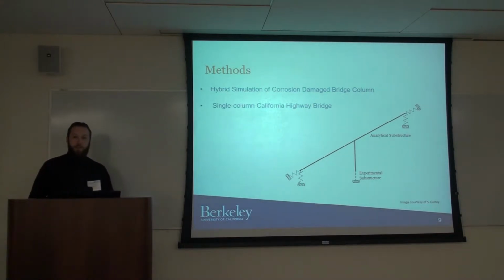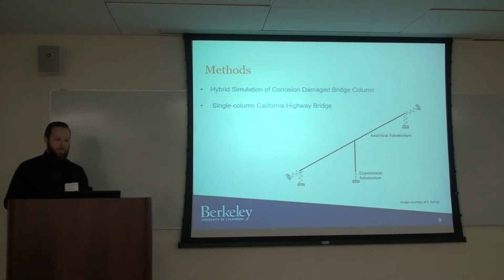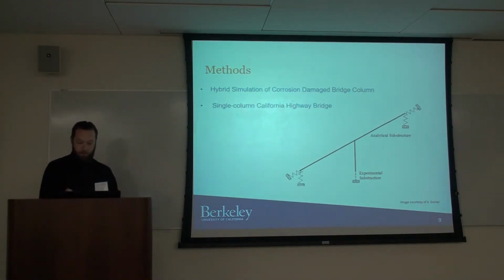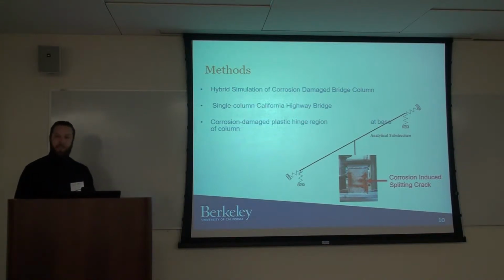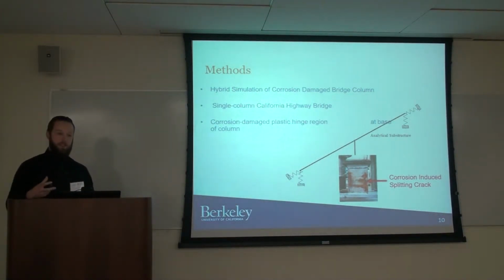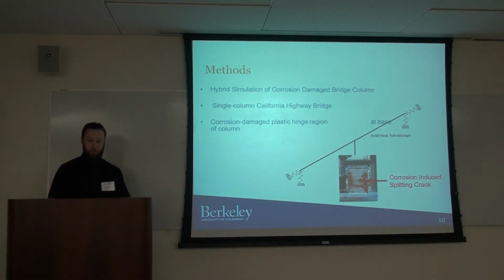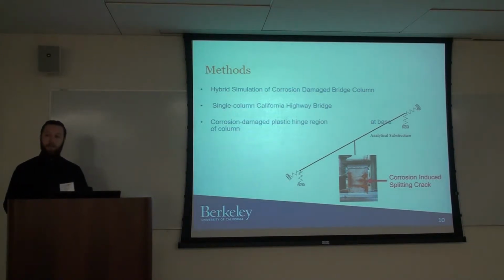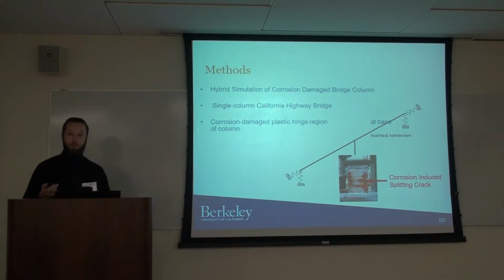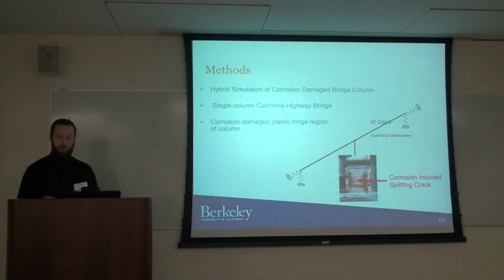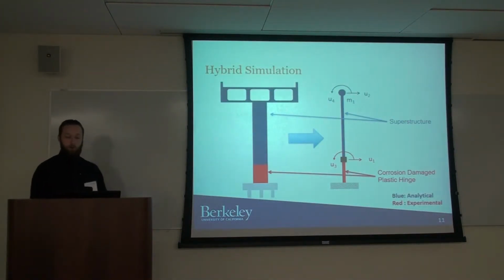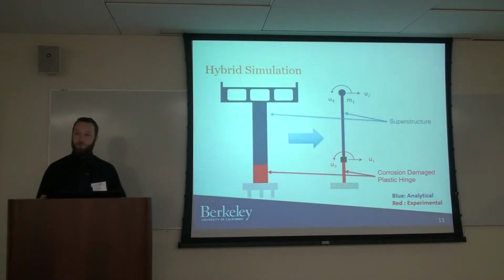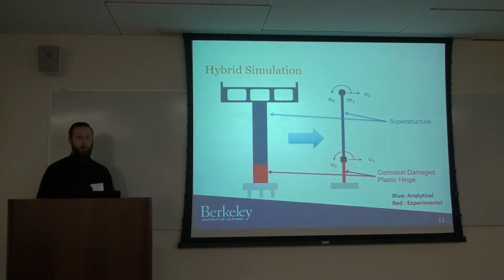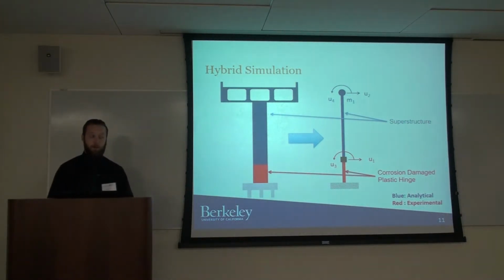So the bridge of interest that we're considering is a single column California bridge structure. And we see that we have an analytical substructure, and we've replaced the plastic hinge with an experimental substructure. This is just a concrete column section, and it has been separately corroded and with splitting cracks induced, similar to those that we saw in the image I showed before. And if we replace this portion of our OpenSees model of the bridge structure with this pre-damaged substructure, we can capture the complexities of damage and incorporate those into our OpenSees model without having to explicitly model them.